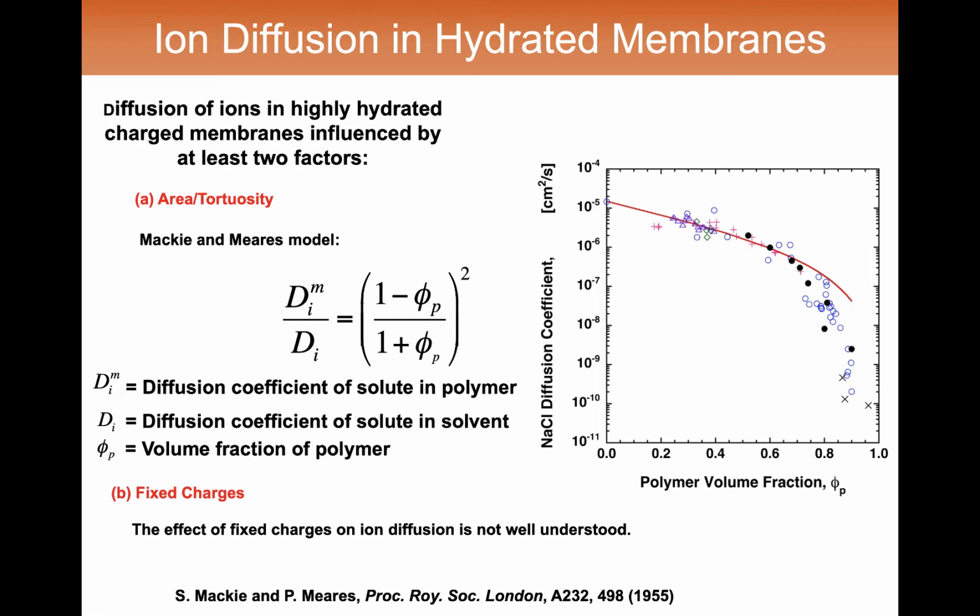And you might imagine that the reason for this is that at low water content, there's going to be a fundamental change in mechanism, that eventually the water content is so low and the polymer chain segments are crowded around the ions to such an extent that in fact it becomes the polymer segmental motion that gates the transport of ions through the material.